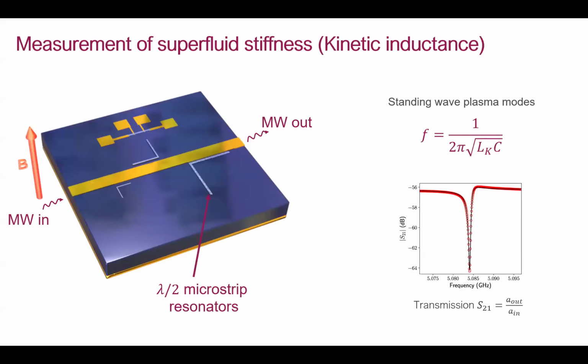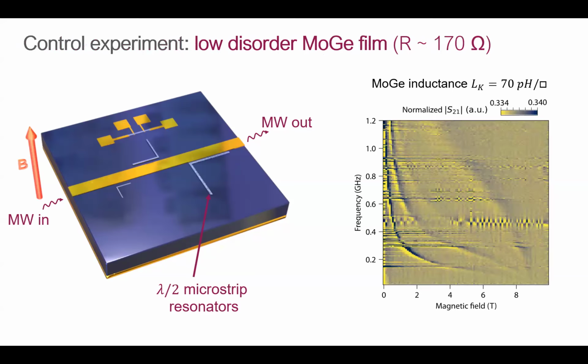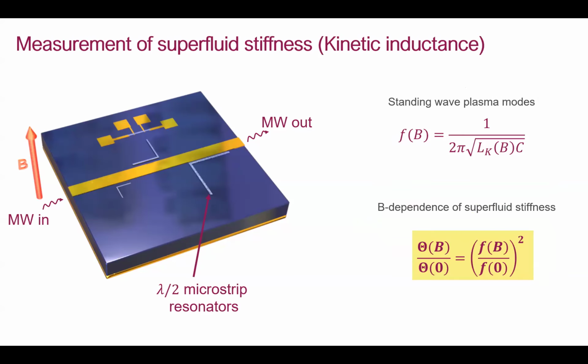So we use a modern technique compared to simple magnetotransport to measure the superfluid stiffness. We actually measure the kinetic inductance of superconducting resonators, which are made by coupling a strip line of indium oxide to a transmission line where we pass microwaves through. If we know the capacitance of this strip line, we can very simply, from the resonant frequency of this resonator, get back to the inductance. And if you apply a magnetic field, the capacitance is independent of magnetic field. So what you can measure is the inductance as a function of B, and the superfluid stiffness is just proportional to the frequency squared. This is a very straightforward and powerful method to measure the superfluid stiffness at T equals 0 as a function of B.